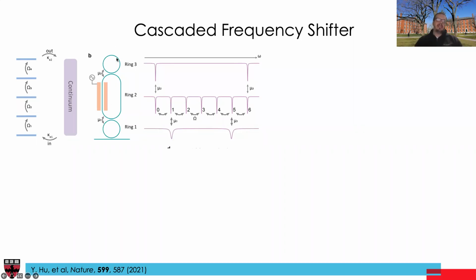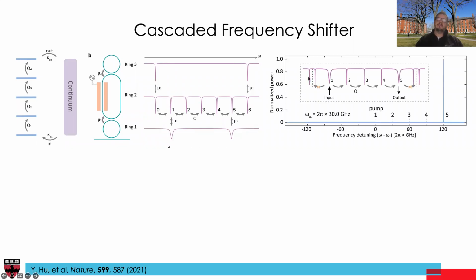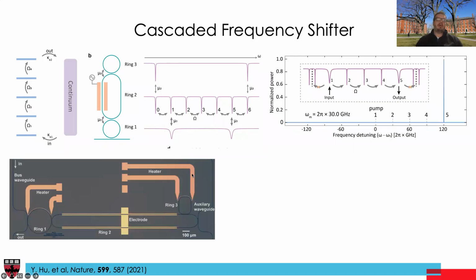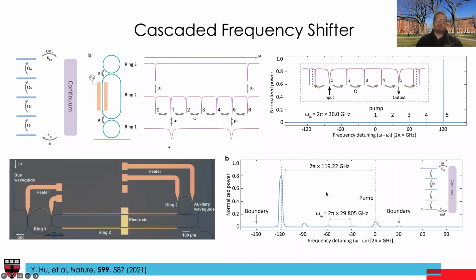But if you bring this ring here, I use it to break the symmetry of the system, or to break this periodicity. So what this ring does, I tune the resonance of this ring to the resonance of this ring. Basically, this resonance is tuned to this resonance, and they are strongly coupled. They introduce splitting. And this splitting breaks the periodicity. So now light cannot go this way because it's a mirror, essentially. Light can only go this way, and then it has to get out, it cannot go forward because there's no periodicity anymore. And indeed, we fabricated this, and indeed it works as promised.